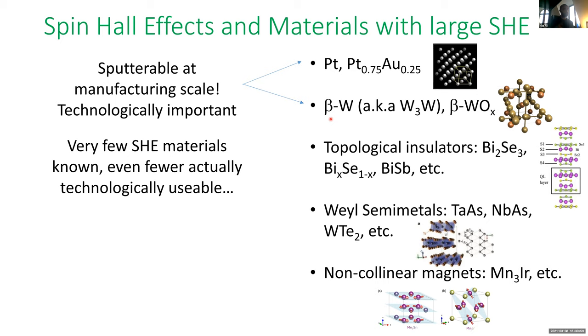So again, tungsten rears its head, and an oxygen-doped version. There had been a lot of speculative work that have now been confirmed to various levels in topological insulators, Weyl semimetals, and noncollinear magnets. But all of these materials had one important drawback. The drawback being that there's an entire infrastructure set up to make all of your devices, computers and phones and whatever, and they all are based on sputtering, physical vapor deposition. So platinum and tungsten were the only ones out of all of these that could immediately be plugged into the existing infrastructure to make these type of devices. So again, platinum was known, but actually beta tungsten had been experimentally shown, but it wasn't explained why beta tungsten had such a large spin Hall effect.